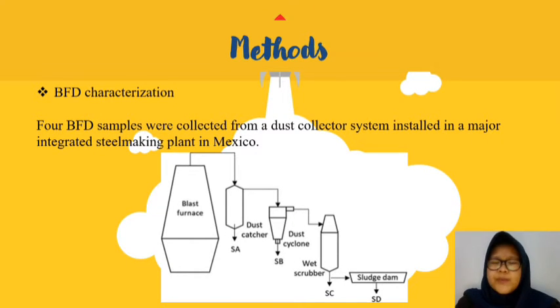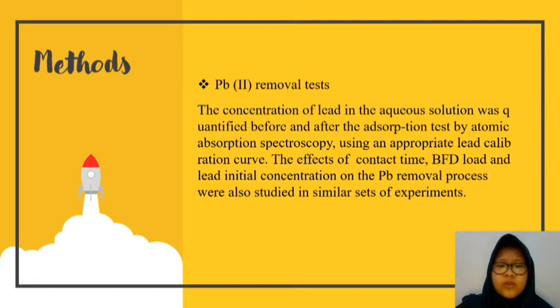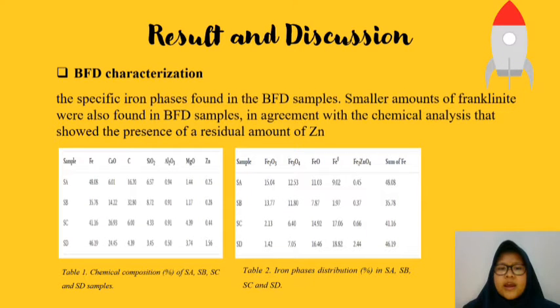The method used in this journal is experiment. The first experiment is BFD characterization. Four BFD samples were collected from the dust collector system installed in a major integrated steelmaking plant in Mexico. We can see in the picture in the slide the BFD characterization. The second method is the Pb2+ removal test. The concentration of lead in the aqueous solution was quantified before and after the adsorption test by atomic absorption spectroscopy using an appropriate lead calibration curve. The effect of contact time, BFD load, and initial lead concentration on the Pb removal process were also studied in similar sets of experiments. Result and discussion.